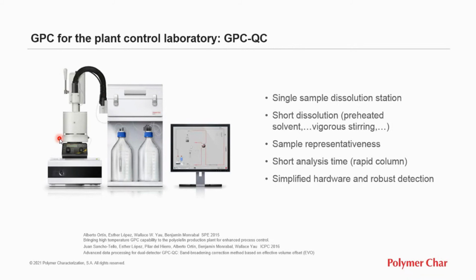Sometimes, depending on the process, a significant amount of sample may be required to get good representativeness. Large capacity vials of 100 or even 200 milliliters are used in this approach. Up to 200 milligrams of polymer can be dissolved for analysis. The shortest analysis time is possible by using a single fast GPC column. Both time and solvent used are minimized. Reliability is improved by simplifying the hardware and using robust detectors. The analytical workflow is quite simple and requires minimum manual work.